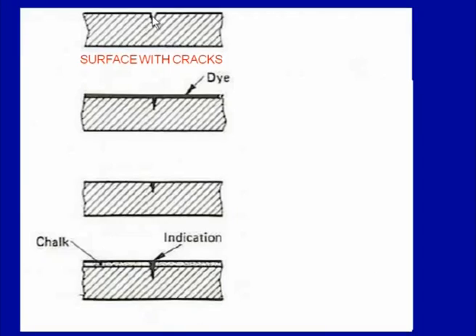So, here, first the surface has some sort of defect, a surface crack. When the dye is applied, the liquid with the dye will be sucked inside the defect. Then that liquid is wiped off, but the liquid which was sucked inside the defect will remain there, and on the application of the developer like chalk powder, stains will come in the chalk powder, and that will show the presence of the defect.